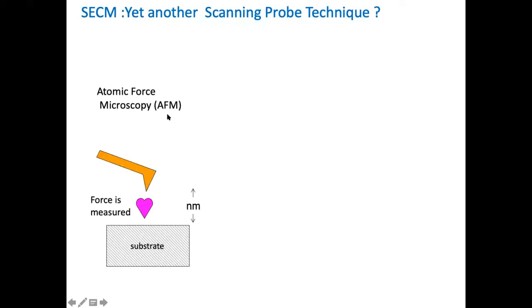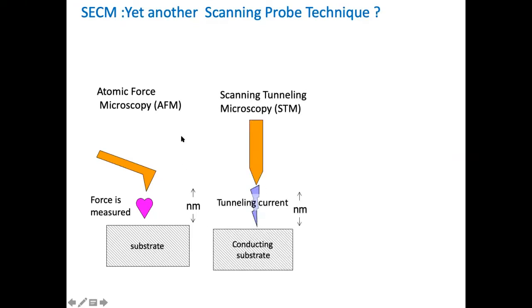Some of you must have used a technique like atomic force microscopy. We call it AFM. In AFM, we are measuring the attractive force, sometimes van der Waals force, between the cantilever tip and the substrate. The substrate we normally use here is an insulating substrate. That's why AFM is useful for biological samples or polymeric samples, where it's not possible to do microscopy with scanning electron microscopy. Normally you go for AFM in non-conducting samples. Here, obviously, we are measuring attractive force between the tip and the substrate, and we raster this and generate the image for topography.